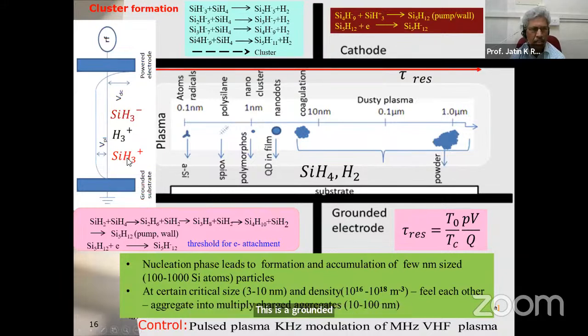So positive and negative ions are formed here. The negative ions are basically trapped inside, because both the electrodes are more negative compared to the plasma bulk. So negative charge cannot go to them; they will be trapped here, whereas they will be bombarded by the positive ions. They will go and bombard there. And of course, neutrals are also depositing.